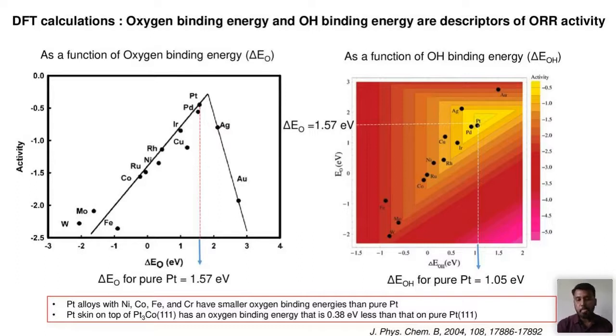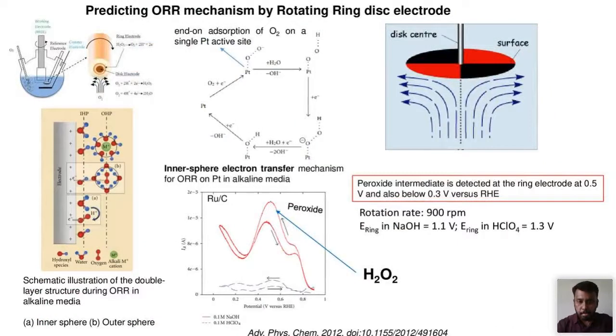By forming some platinum cobalt alloy, or by alloying platinum with nickel and cobalt with a platinum skin, you can minimize the oxygen binding energy. So oxygen binding energy and hydroxyl binding energy are very important. You can easily predict the oxygen reduction mechanism by a rotating ring disc electrode, and based on this experiment you can determine the hydrogen peroxide yield.